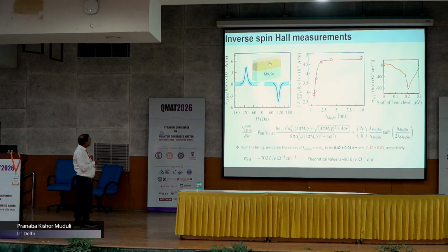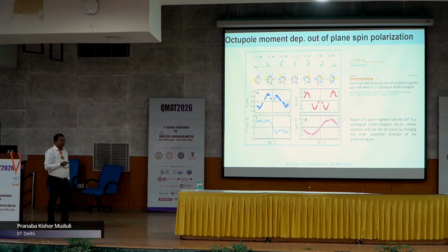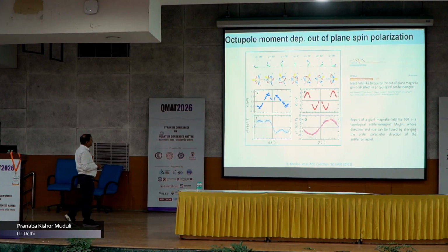So after that, we wanted to investigate this magnetic spin-Hall effect, which is a signature of the quantum material Mn3Ir. Before we did that, a group in Japan led by Professor Otani investigated this. Looking at the Mn3Ir structure up here, these are the actual orientations of the blue and red manganese, but you can describe this entire thing by this octopole moment, which is shown in yellow.